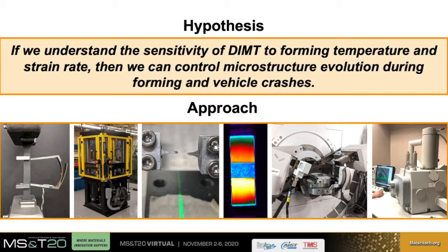First, in order to measure mechanical properties of our Q&P steels, we used uniaxial tensile testing. Second, to evaluate strain state effects on TRIP, we intend to perform formability experiments using a forming press. This forming press is new at the Colorado School of Mines and is equipped with heated tooling and a stereo DIC system. We've also used some novel instrumentation to resolve surface strain, phase volume fraction, and temperature evolution in situ during deformation. The images I'm showing here are from infrared thermography experiments at CSM and Hopkinson bar experiments at the Advanced Photon Source at Argonne National Laboratory.